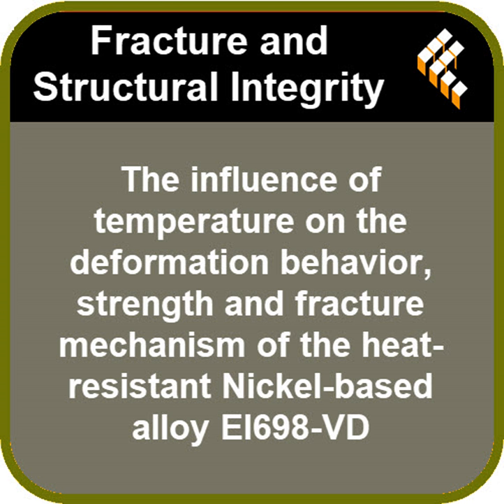But above that 550-degree threshold, it switched. It completely switched to an intergranular fracture. The cracks stopped going through the grains and started going around them. The metal was literally unzipping along its seams, like the mortar in a brick wall just dissolving. A perfect analogy.